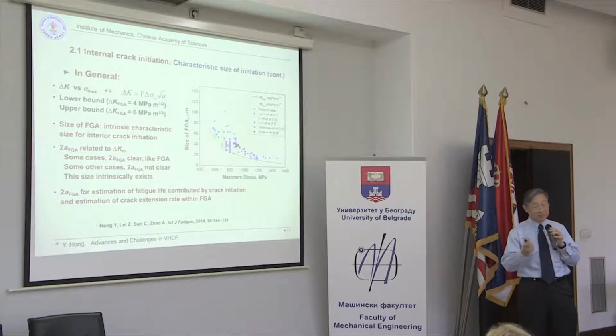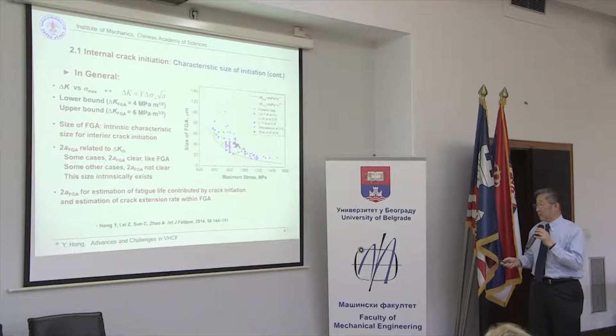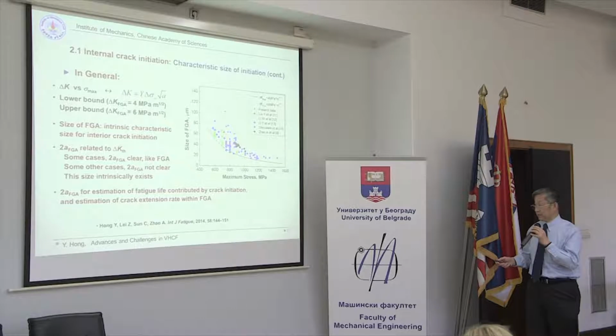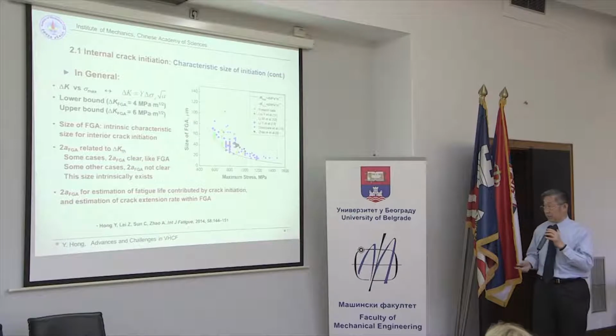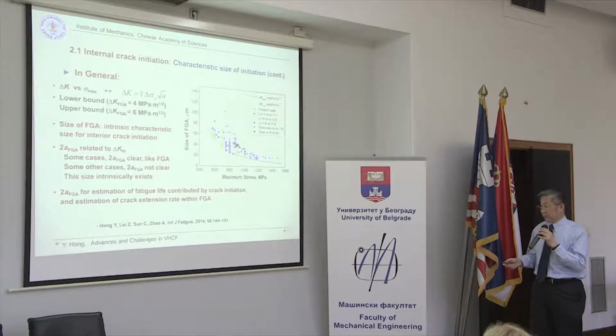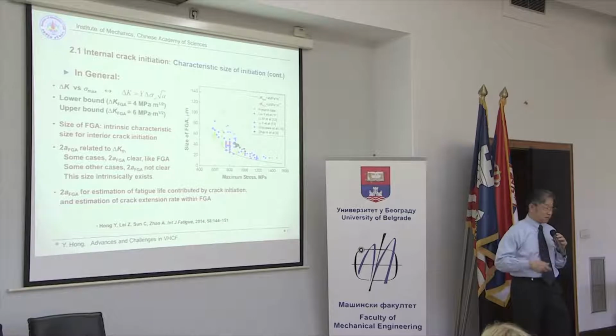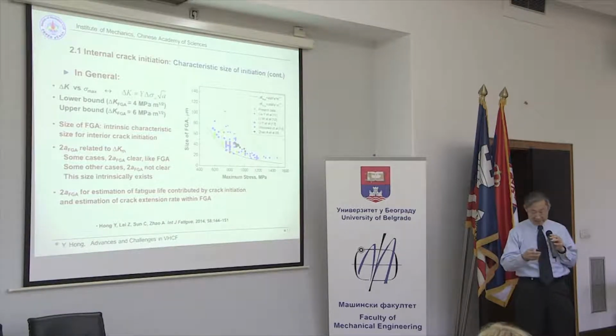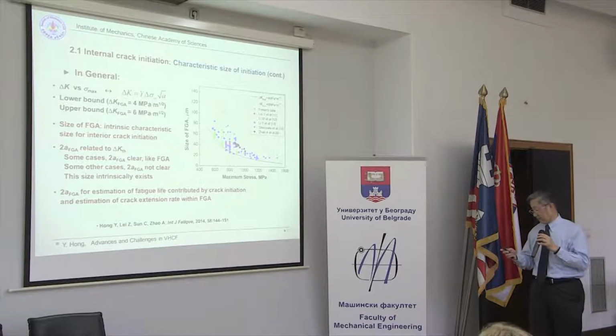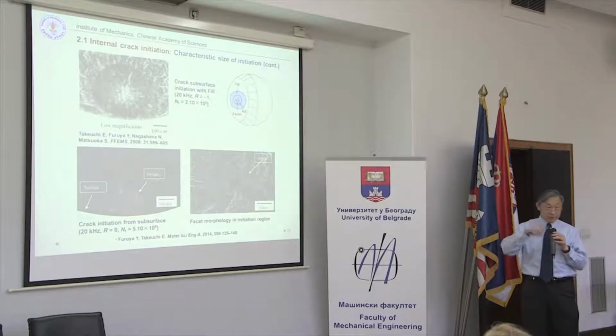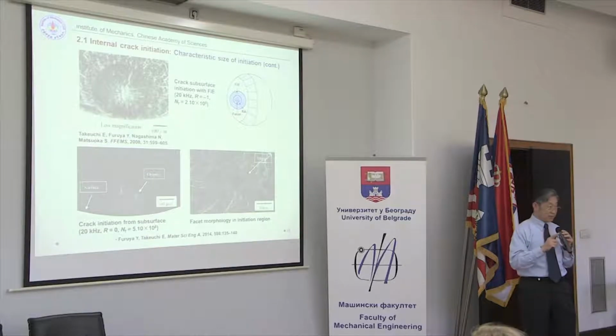So it's very interesting. And then we say that the size of FGA is an intrinsic characteristic size for interior crack initiation. So this is our consideration, we try to propose the concept for very high cycle fatigue behavior. And the previous ones are the cases of high strength steel.